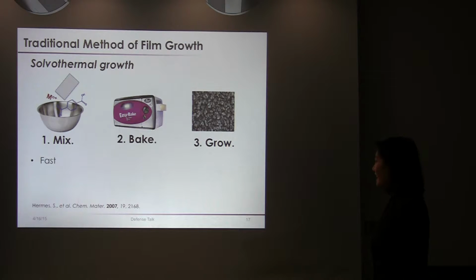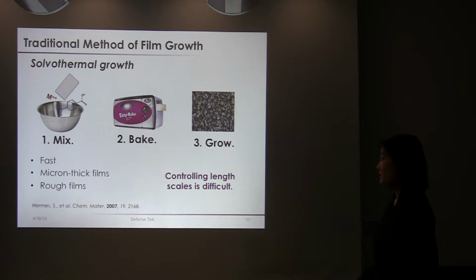MOF crystals. And what this technique allows is that it's very fast. You get very micron thick films, as well as pretty rough films. So even though this process gives you these advantages, it's very difficult to control the length scales with just solvothermal growth. And it's difficult to form films of desired thickness.